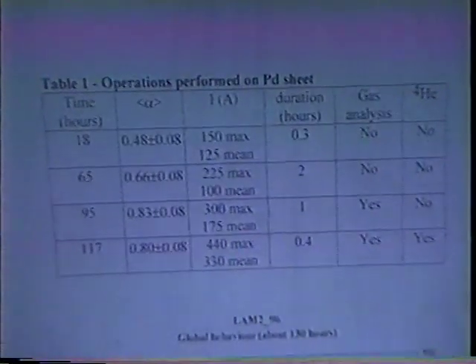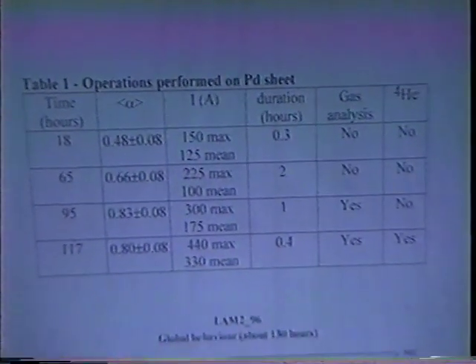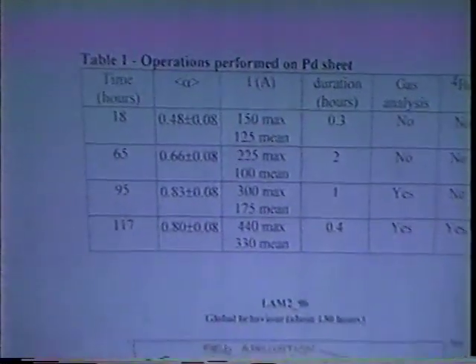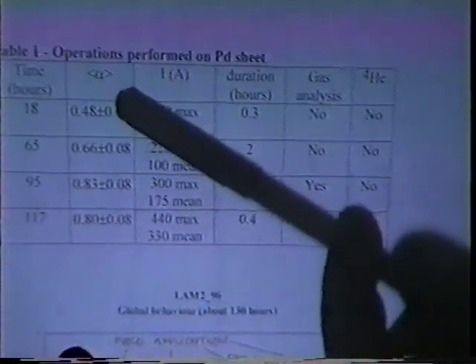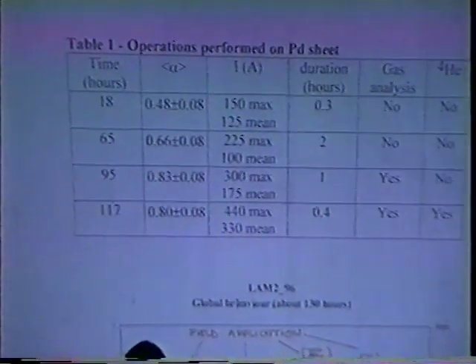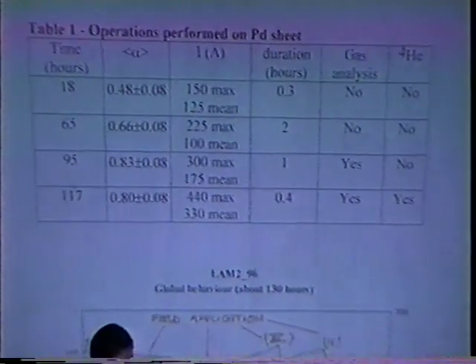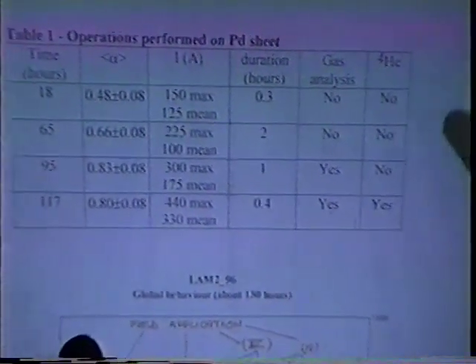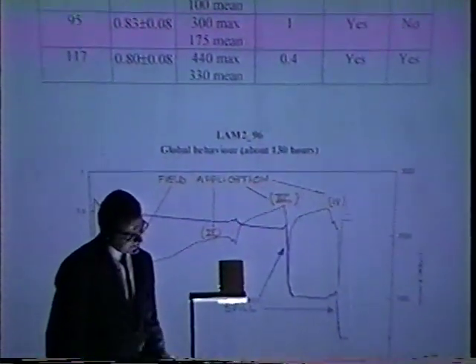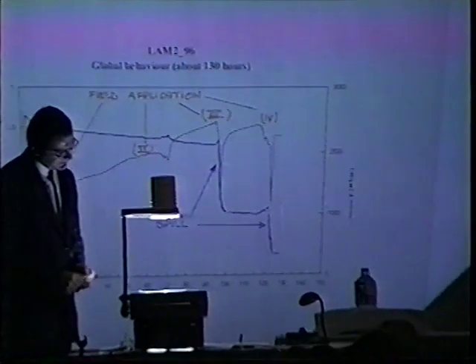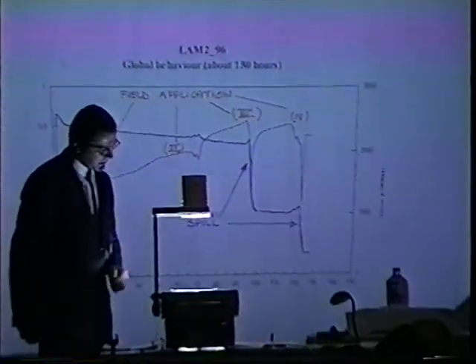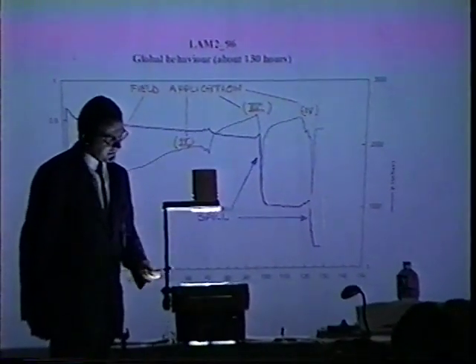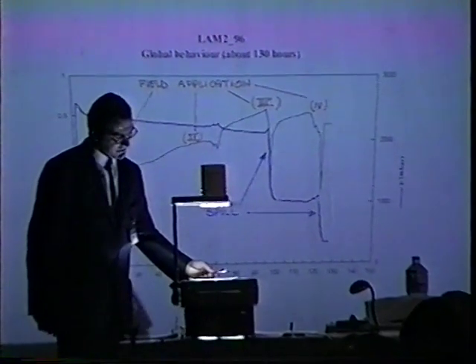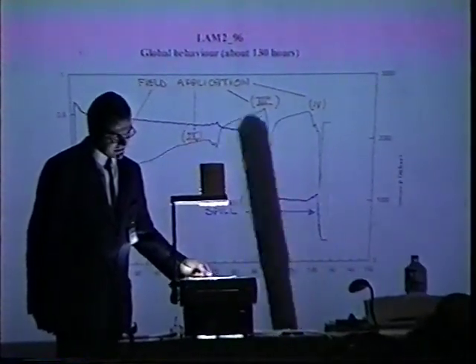I shall now explain the experimental conditions that are summarized by this table and perhaps better by the plots below. The first column reports the hours since the gas emission in the cell, with the loading ratio performed after that time, the current applied to the sample, its duration, and whether gas analysis was performed. The last column reports whether some helium-4 presence was detected. On the plot below, the violet line represents the pressure, while the black one, the loading ratio. So, regions of applied field are present, one after about 18 hours, one after about 65 hours, and so on till the end.